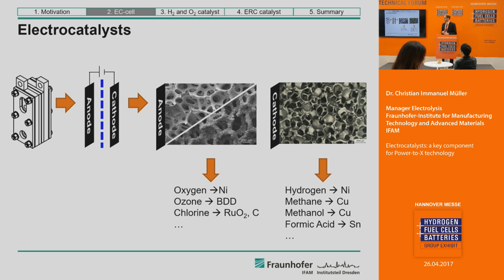Such an electrochemical cell comprises an electrode, an anode, and a cathode. These electrodes are divided by a diaphragm or separator in order to ensure that you get really pure products. And by the selection of the material we are using, we can define which product might be produced. For example, on the anode side, if we use nickel, we can produce oxygen. If we want to produce ozone for wastewater treatment, then we can use boron-doped diamond, for example. Or we can use other catalysts, for example, to produce chlorine.